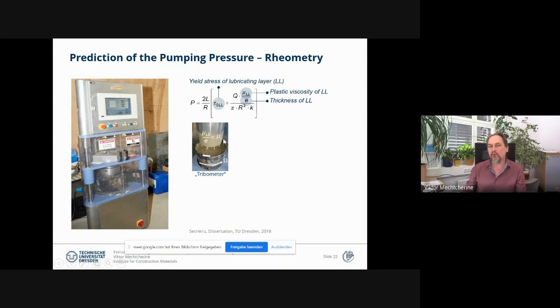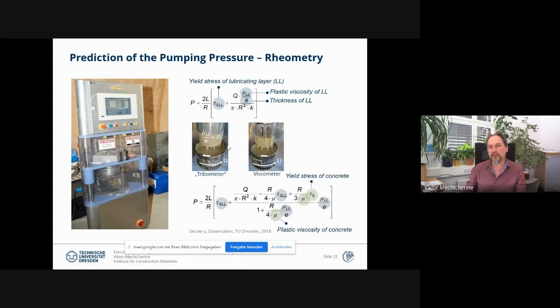So if we have a more flowable concrete, then we need another formula where additionally to these two parameters, we also consider yield stress and plastic viscosity of the concrete itself. And in this case, additionally to tribometer tests, we perform also viscometer tests. Okay, using these parameters, we can establish the relationship between the delivery rate and the pressure needed to achieve this rate, depending on the consistency of concrete and formation of the lubrication layer.